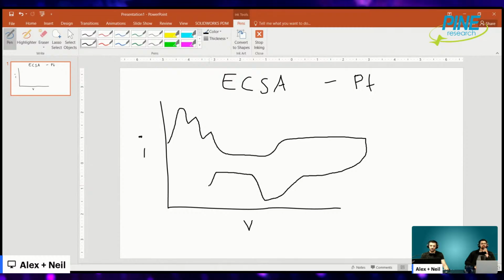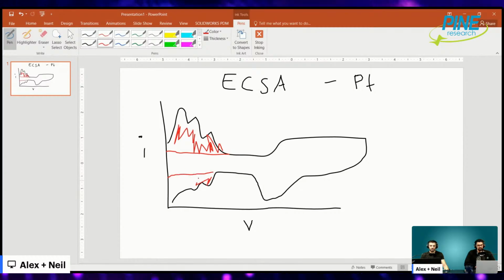I don't have any space, that's why that oxygen reduction looks terrible. What we do is we basically get the area under this part and/or this part. Because this right here is the platinum hydrogen desorption up here, and down here I have the platinum hydrogen adsorption. And I actually have the original reference, I dug it up once upon a time, where this comes from.